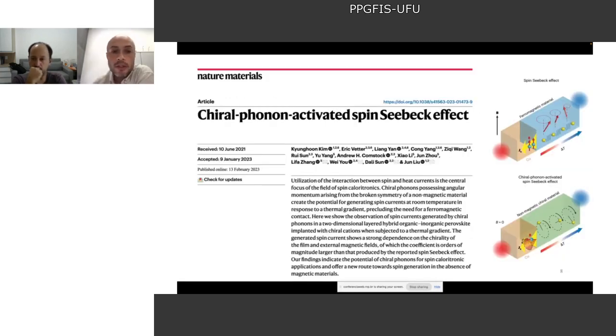Another example of an application is in this paper, where they create a device with a chiral phonon activated spin-Seebeck effect, and in this case they chose a perovskite, a two-dimensional layered hybrid organic-inorganic perovskite, to replace the ferromagnetic material. So in the traditional spin-Seebeck effect, you need to apply a magnetic field, you need a ferromagnetic material, but when you use chiral phonons, you don't need a magnetic material. This is a non-magnetic chiral material, and also you don't need the external magnetic field. So you can see that with the use of chiral phonons, you can produce a much simpler device where you don't need to apply an external magnetic field.